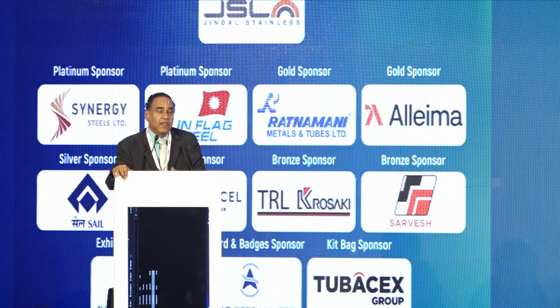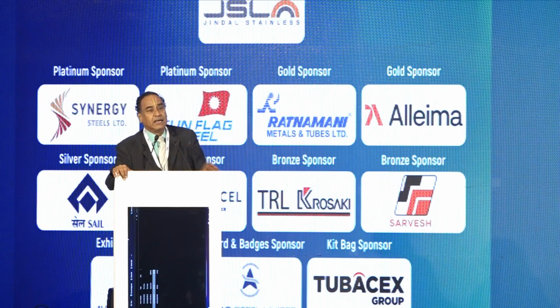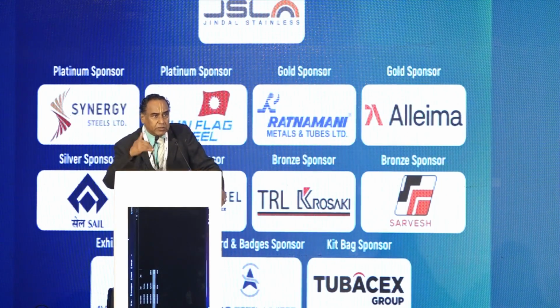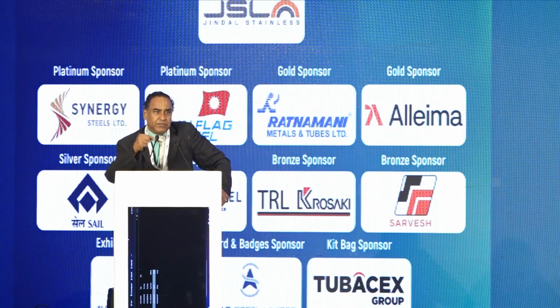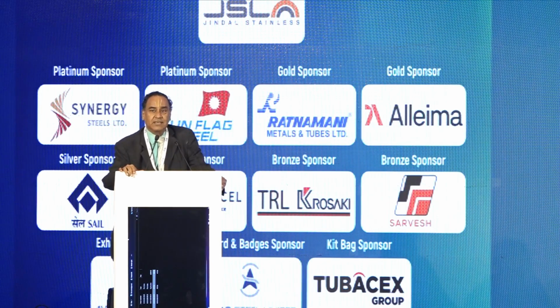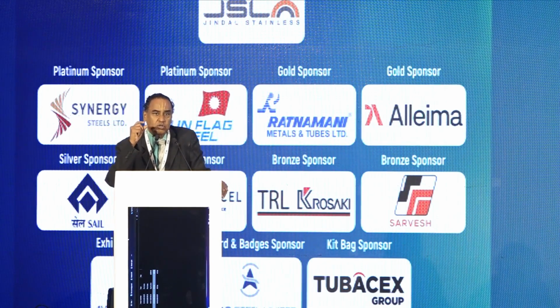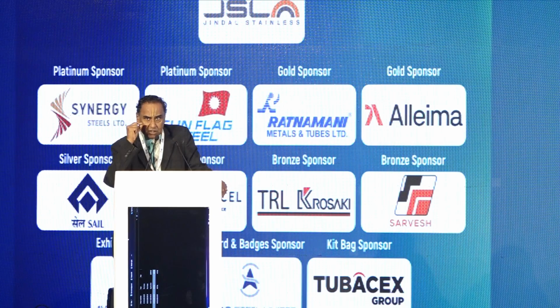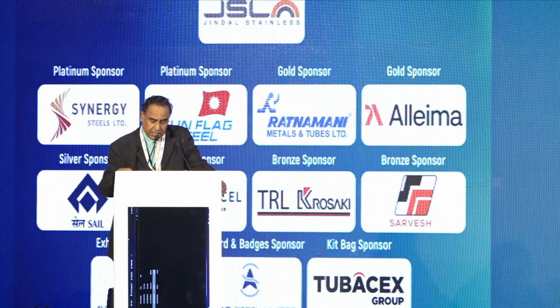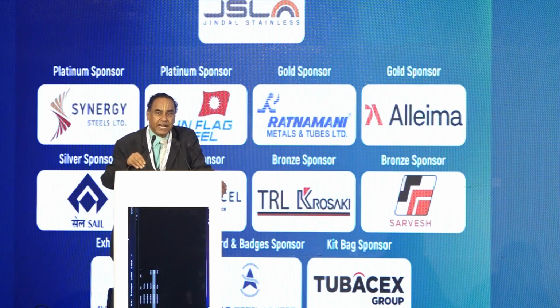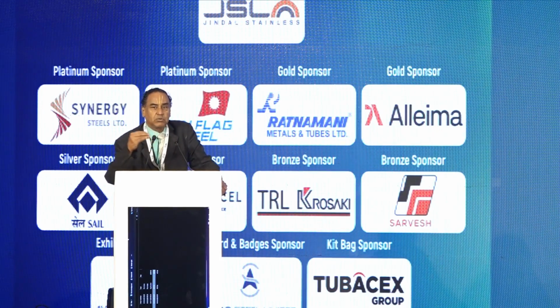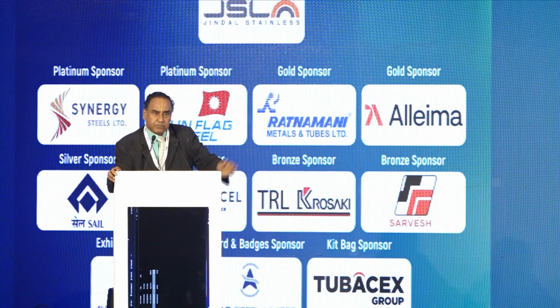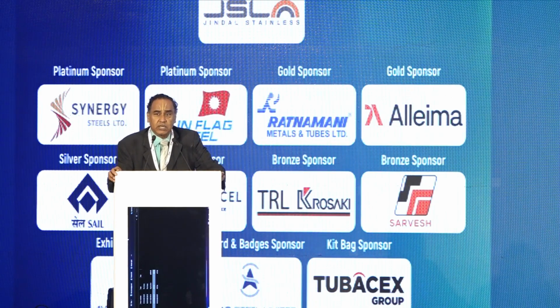Then 304, when the stabilized grades are called, with titanium is called 321, with the niobium is called 347. When the molybdenum is added for imparting specific corrosion resistance or high temperature properties, it's called 316. And when the carbon content is controlled to give better corrosion properties under certain conditions, it's called L grades. There are low carbon grades, 316L. Like that, then titanium is added to stabilize.